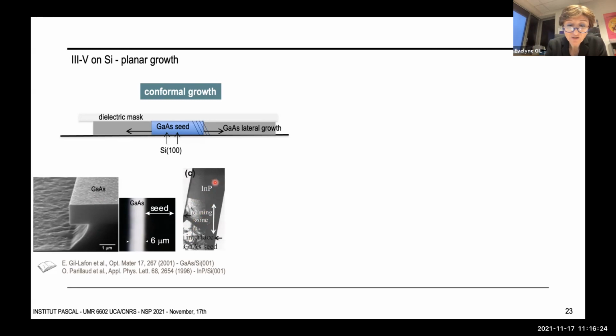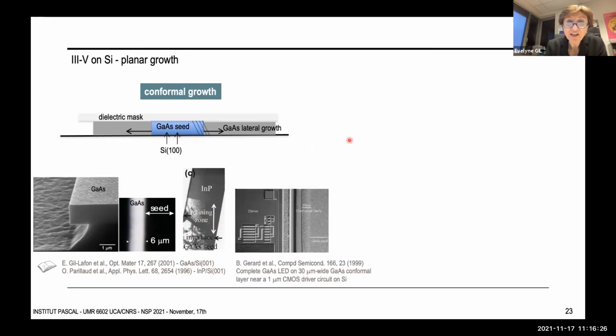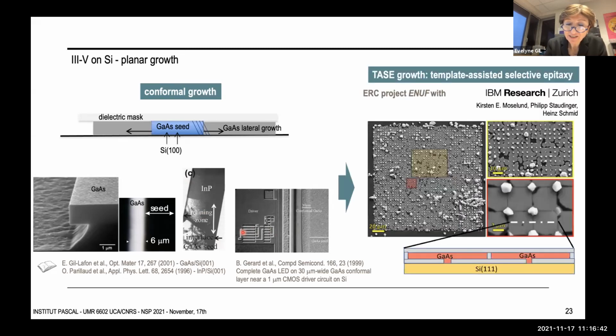And as a final demonstration, you have here a complete gallium arsenide LED grown on 30 microns wide gallium arsenide conformal layer near the CMOS driver circuit on silicon. So recently, IBM and Institut Pascal worked again on the idea of growing inside cavities from gallium arsenide seeds to obtain gallium arsenide buffer layers and sufficient crystal quality after coalescence on silicon.